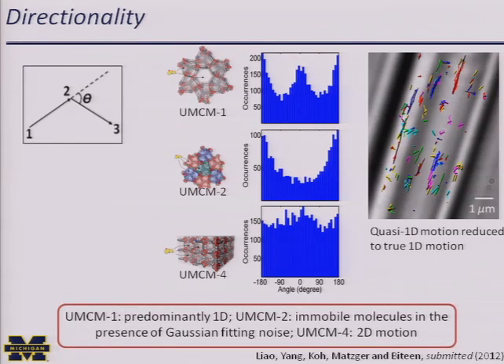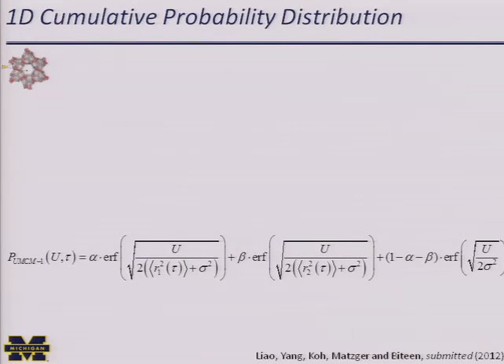So we analyzed UMCM1 according to the 1D cumulative probability distribution. A nice thing we could do with the CPD is put in several terms. So here we have one term, two terms. They look about alike, but alpha and beta are weighting coefficients, and these can have different diffusion coefficients that come out of R squared, out of the MSD, by that Einstein equation. And then we also have an immobile term, such that all these components add up to 100%.